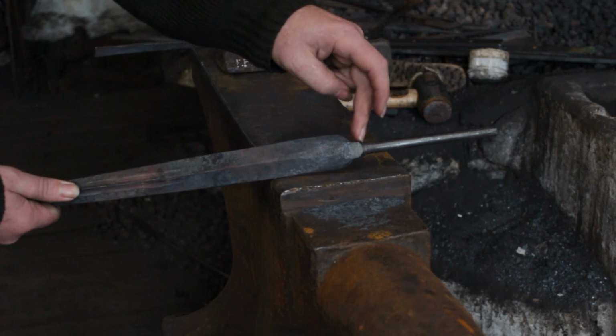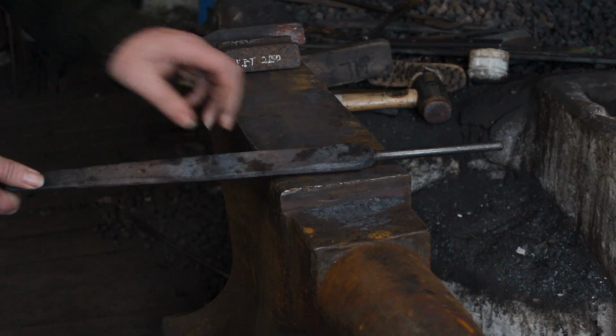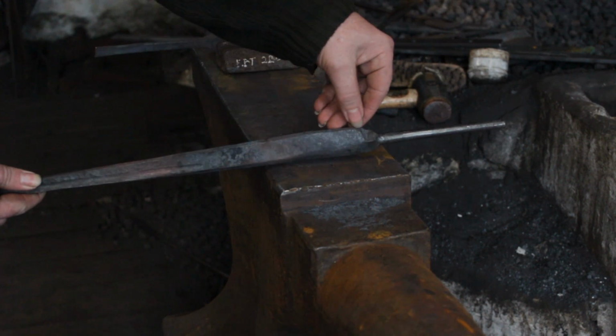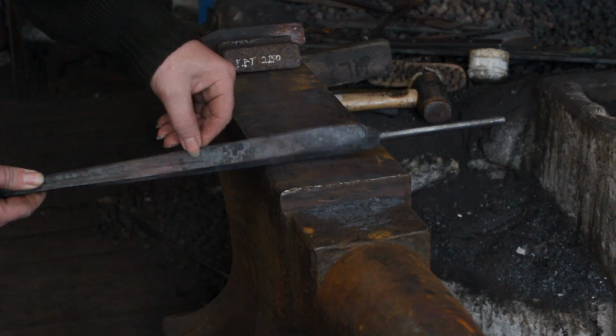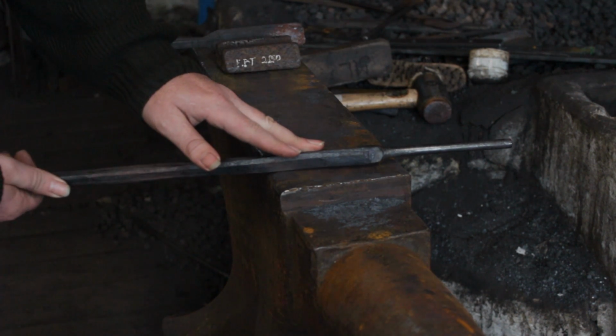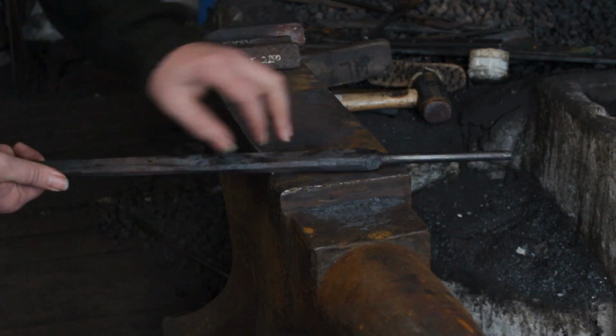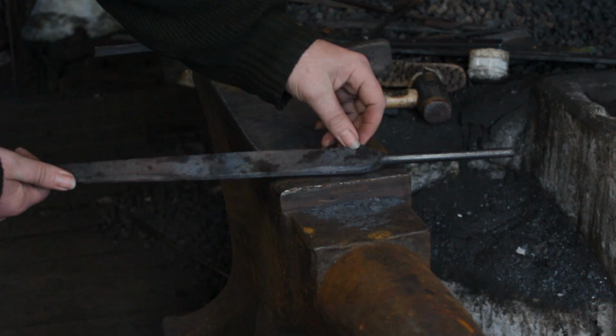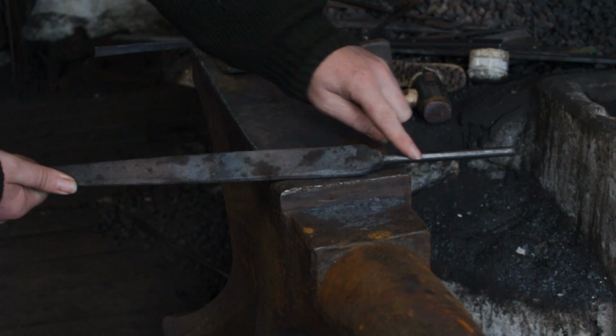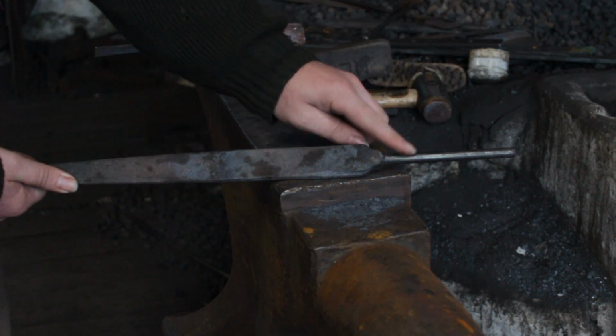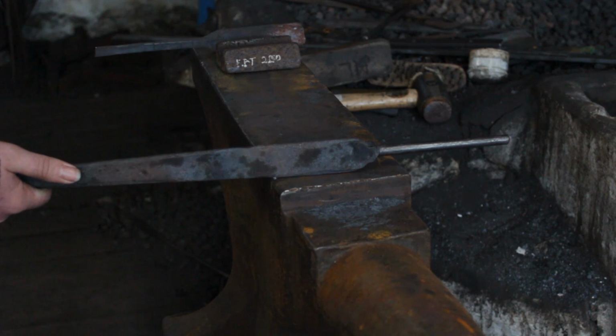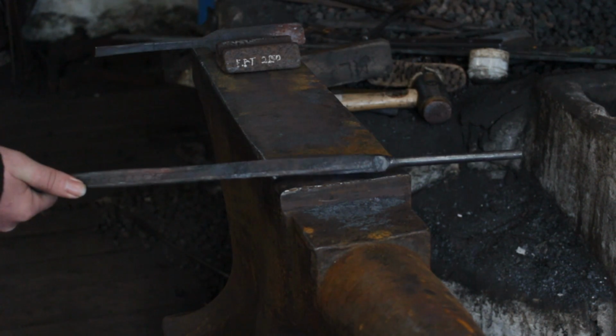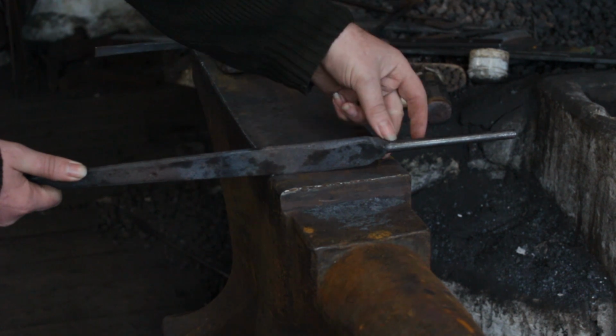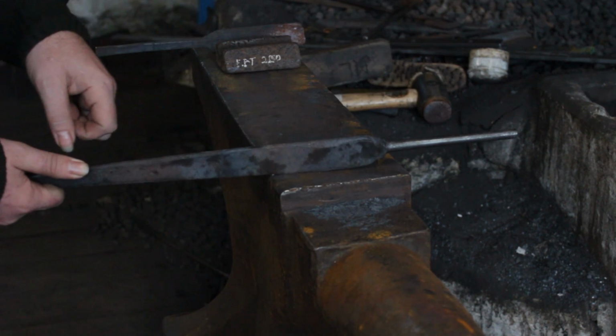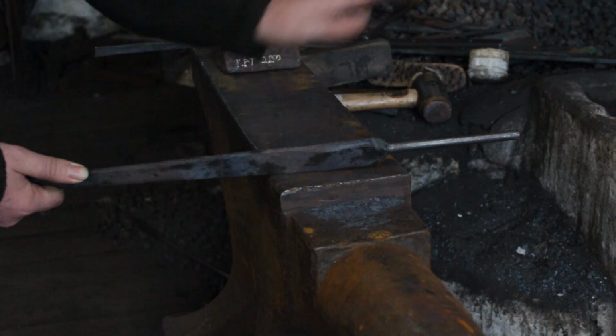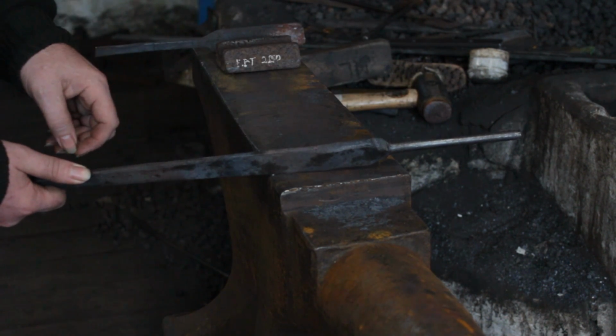So now I actually left this square section here because when we go to grind the bottom of the blade, we need to remove about 5 or 6 millimeters of thickness from the blade. Again, I made that deliberately oversize. When we go to grind down the flat of the blade on the underside, we don't want to be flattening the bottom of the tang eye at the same time. This needs to stay at this thickness. So I've left that square, so that I can use this to physically push the tang away from the bottom of the blade, which we'll be doing today. And I've got enough chunk there that it won't cause any distortion or anything like that, hopefully.